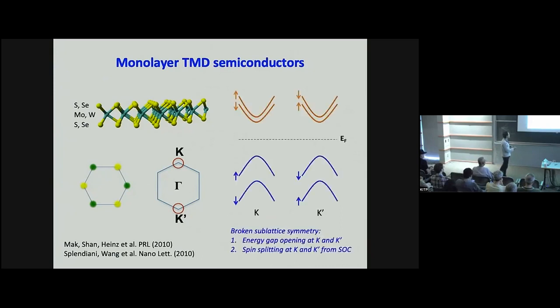And this is a very simplified band structure, taking into account spin-orbit interaction. So in the absence of inversion symmetry in the system, you can think of it as graphene, but then you open up an energy gap at the K and the K prime point. So there's an energy gap here. It's about 1 to 2 eV. It's a large gap.